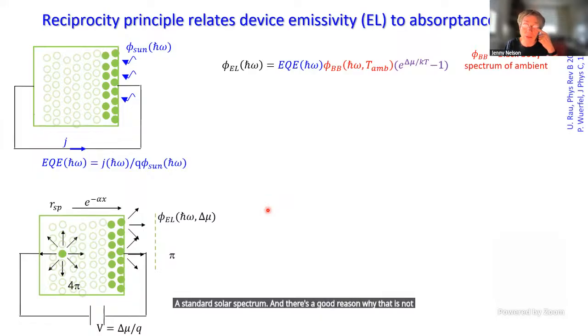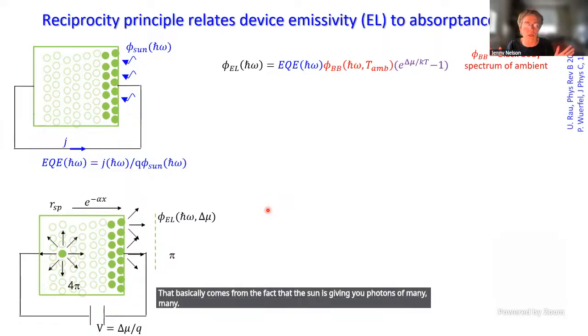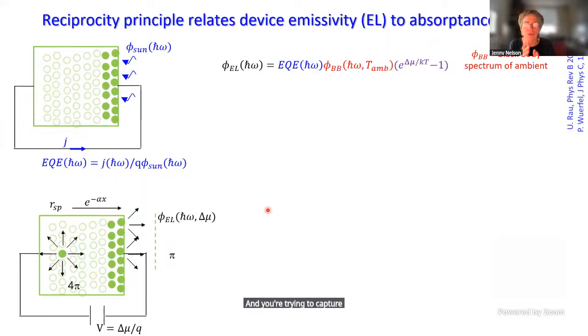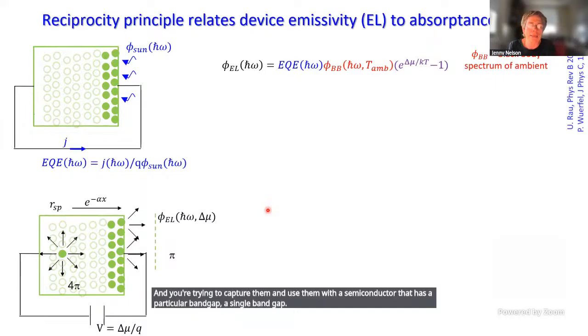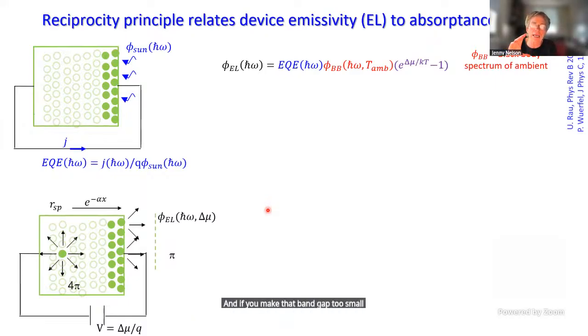There's a good reason why that is. It basically comes from the fact that the sun is giving you photons of many different energies at once, and you're trying to capture them and use them with a semiconductor that has a particular, single band gap. And if you make that band gap too small or too high, you won't get a high power conversion efficiency. There's an optimum where you get the best, just about in the near infrared, and it will give you, in theory, a power conversion efficiency of the low 30s, 31 to 33%. Now that's where we would like to get to.